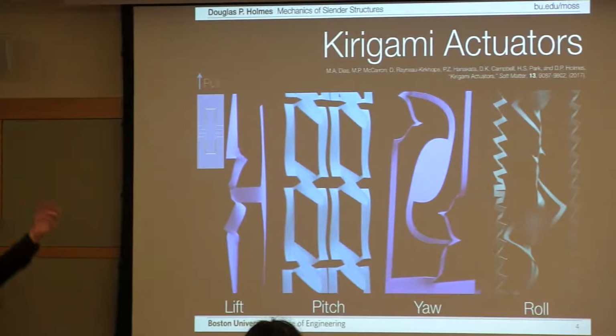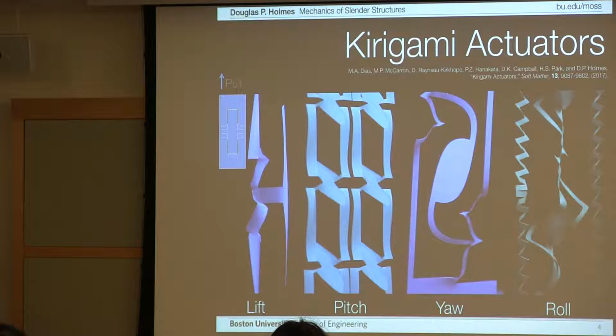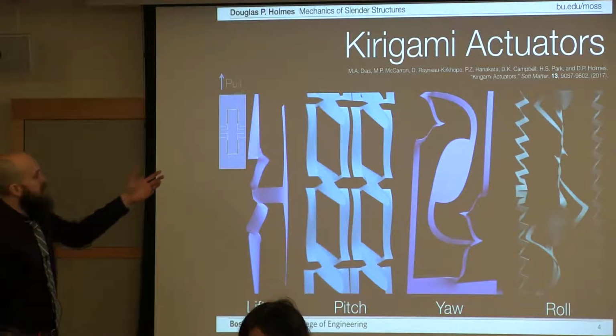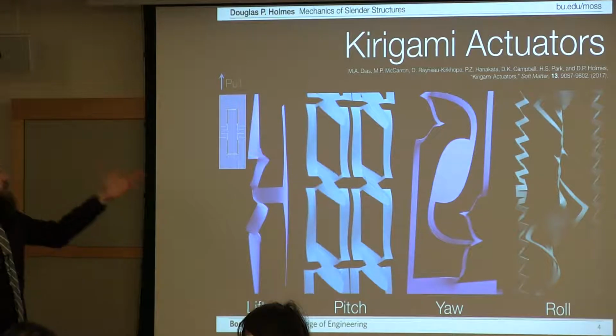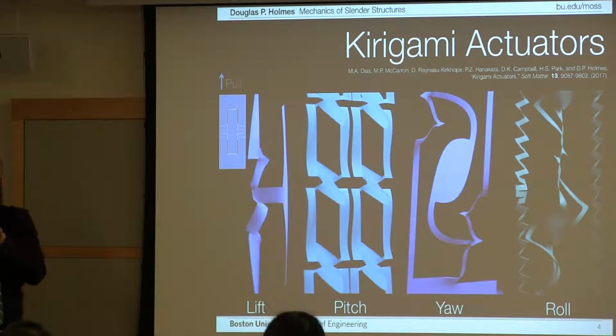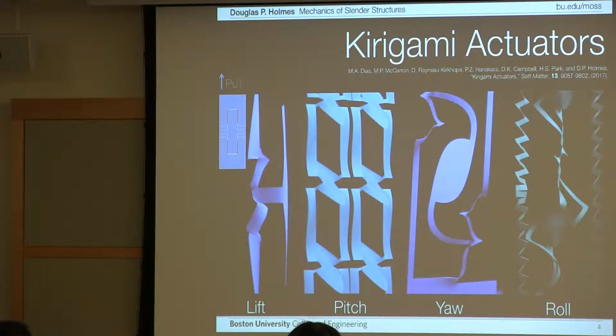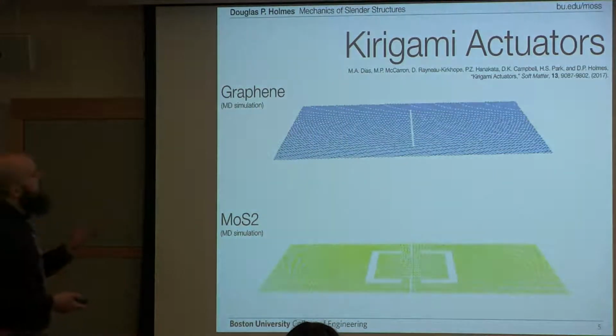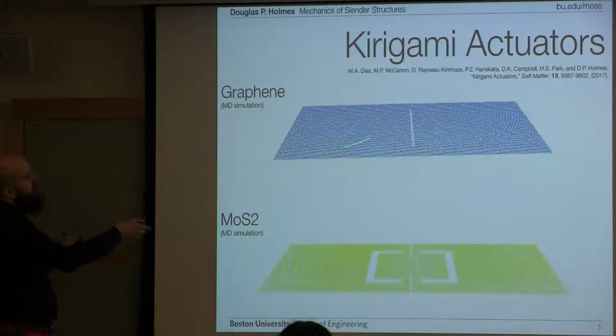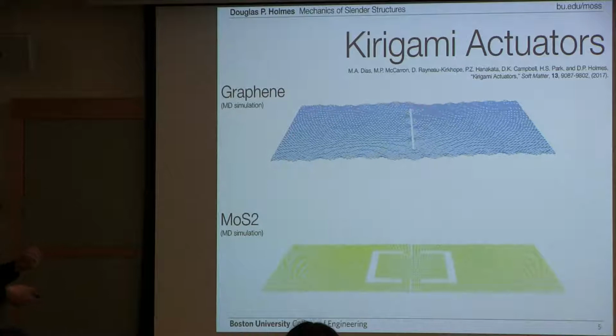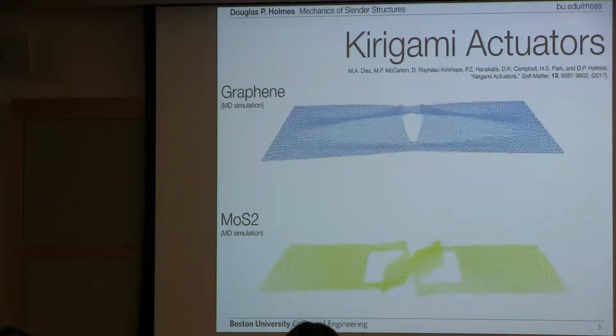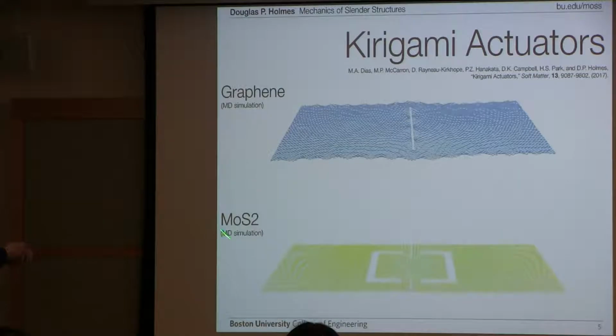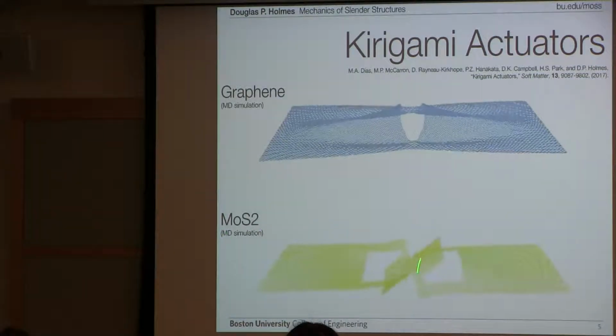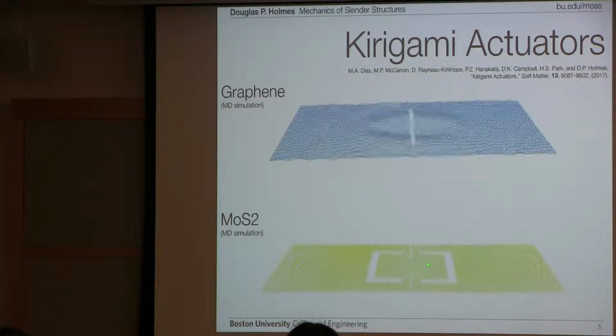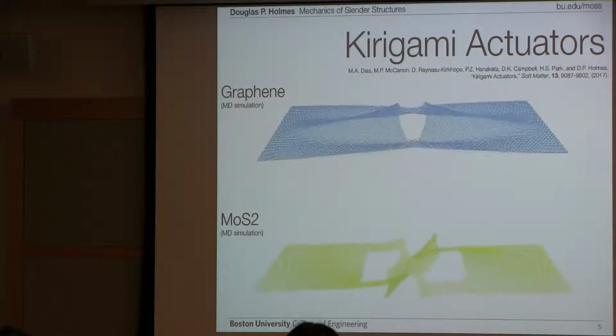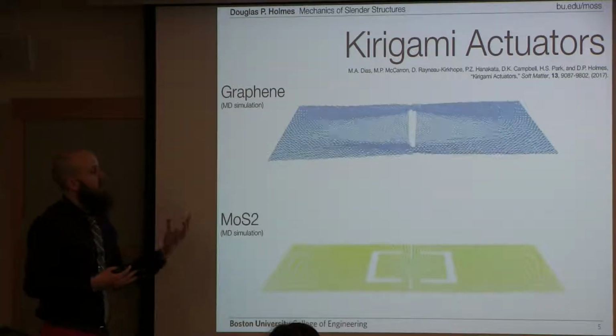But what's particularly interesting is that only the geometry here matters. So we did some math and we showed that the thickness of the sheet doesn't play a role. So if you can just take these cut patterns and make them in the thinnest sheets possible, you'll get the same deformations. So for instance, you could take these all the way down to 2D, look at something like a graphene sheet here with a single cut on it, and you pull on it, and you see the same deformations that you saw in that continuum material on the previous slide. Here's another 2D material, MoS2, in which we've made the same cut pattern that gives you a pitch-like rotation. And you see that you're able to generate rotation in these 2D materials where the only thing that matters is the geometry of these structures.